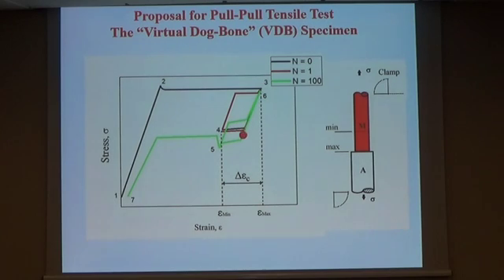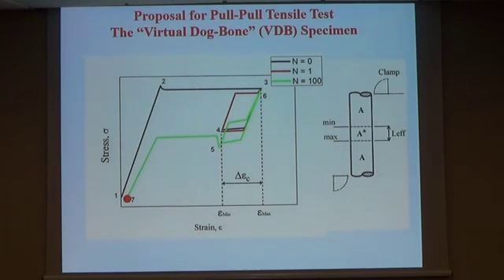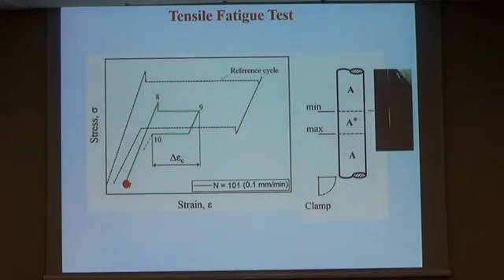After unloading, we have this situation. We have this region, the effective length with functional fatigue, with lower transformation stresses, and the rest has only one cycle. So later we are ready to apply the fatigue test.